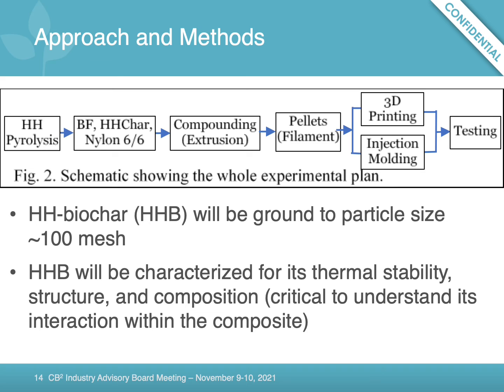So the approach we'll take in this project is we'll take hemp hurd and pyrolyze it, and then take the hemp hurd biochar and compound it with basalt fiber and polyamide in an extruder to produce pellets, which will be then used to make filaments for 3D printing, or fed into an injection molding equipment in order to produce composite material for performance evaluation. Hemp hurd biochar will be ground to a particle size of approximately 100 mesh.